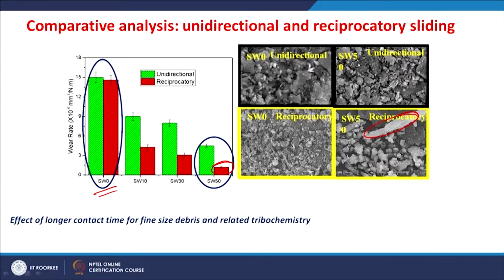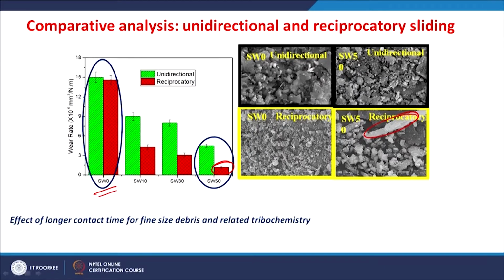Those cylindrical debris generally facilitate easy sliding, and the cylindrical debris generally forms only when there is a viscous surface. This viscous surface layer is because of the interaction with the silicon oxide present on the silicon carbide particles or formed due to the wear test. This silicon oxide reacts with the moisture and forms a silicon oxyhydroxide. These particles connect to each other and form cylindrical debris. So, the viscous surface is removed from the composite and the debris are connected to each other and form a cylindrical shape.